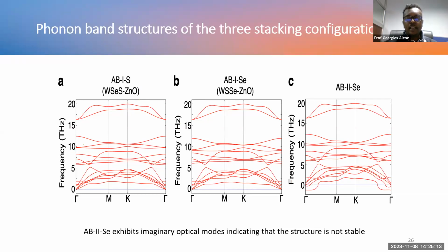the phonon band structure for the three systems. If you see in C, you can see that it has imaginary optical modes on the negative side. And this means the system is not dynamically stable. If it is not dynamically stable, it is not interesting to fabricate it. It is not easy to fabricate it and realize it experimentally. So we excluded this heterostructure, and our study continues on the two heterostructures, which are dynamically stable.